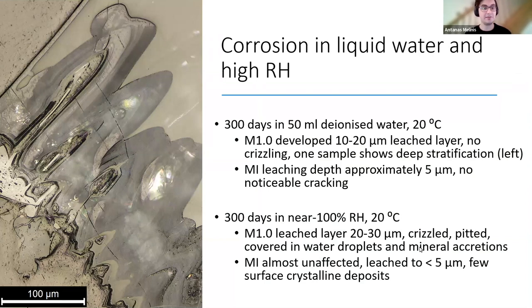Again, quick rundown of the most popular methods of accelerated corrosion in water. They were tested for both the MI and M1.0 glasses, and the most interesting results came after as long as 300 days, so better part of the year. In general, in both exposure in liquid water and near 100% humidity in the sealed container, the M1.0 suffered much more, developed thicker corrosion layers, stratification of its hydrated layer, which is very rarely seen in accelerated corrosion and very commonly seen in archaeological pieces. However, this was unfortunately deemed to be too slow. Yet still a very interesting future venue to explore, especially to recreate those sort of lamellated multi-layer structures.